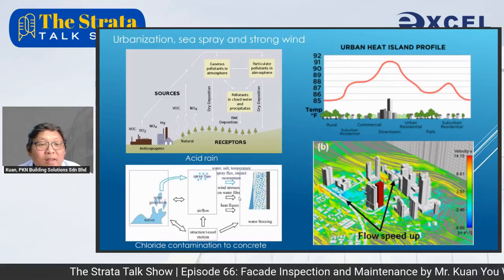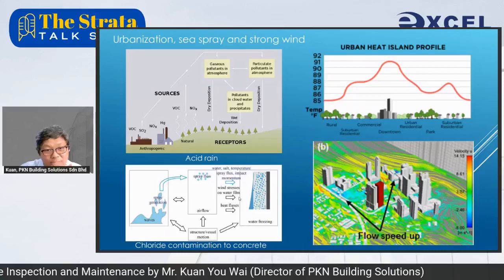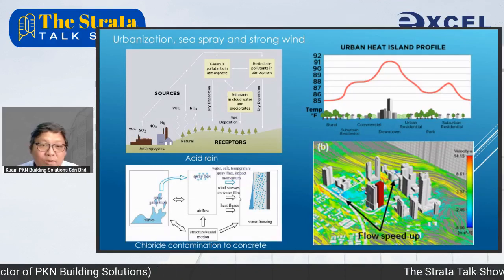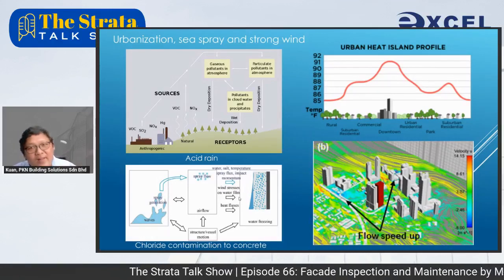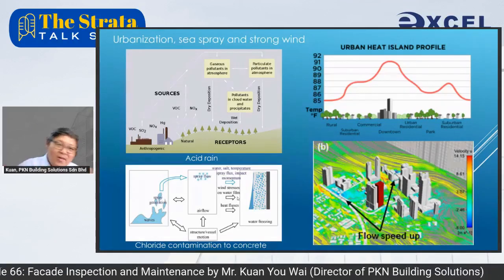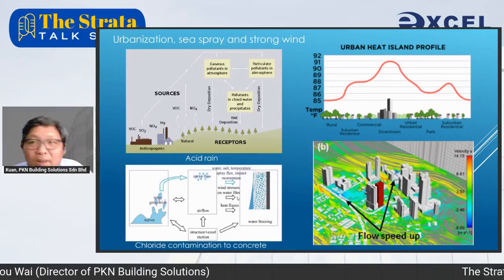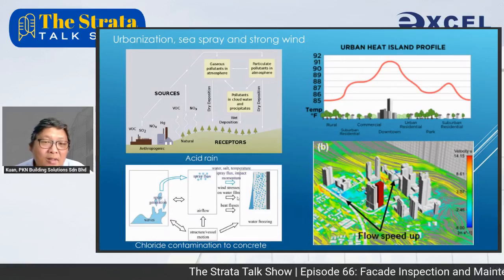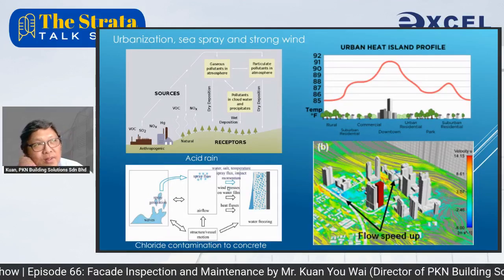And salt spray, sea spray, covers up to 25 kilometers from the coastal site. Actually, it is subjected to sea spray because of the chloride; due to the wave movement and the solar energy given by the sun, the salt ion, the chloride ion, will start to migrate inland up to 25 kilometers. And that's why many years ago my father told me, do not buy a car that was used at the seaside, because the body will corrode very badly due to the exposure to chloride contamination.